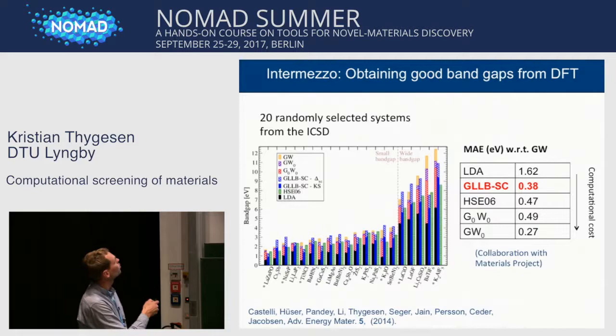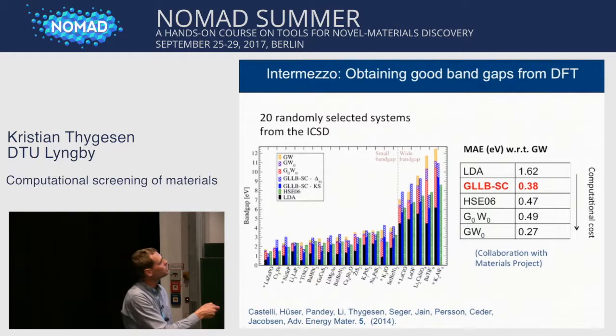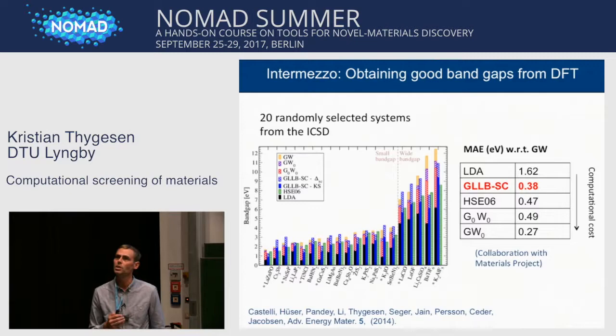And you can see that this is another test where we looked at 20 randomly chosen systems from the ICSD and calculated band gaps with a range of different methods, as you can see up here, and the mean absolute error of all these methods compared to fully self-consistent GW calculations is shown over here. You can see the GLLBSC, which is really not much more expensive than a GGA calculation, is within 0.4 eV of the GW result, which is not perfect agreement, but it's acceptable for a screening study.